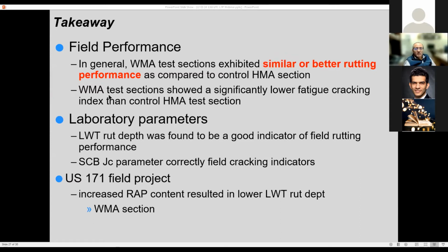And specifically, those WMA sections showed significantly lower resistance to cracking as compared to the control mixture. In terms of laboratory parameters, LWT is a good indicator of high temperature performance, as specified by AASHTO T324. The SCB-JC parameter, as specified by ASTM D8044, is another good indicator for field cracking for the sites that we have measured and the tests that we have done.